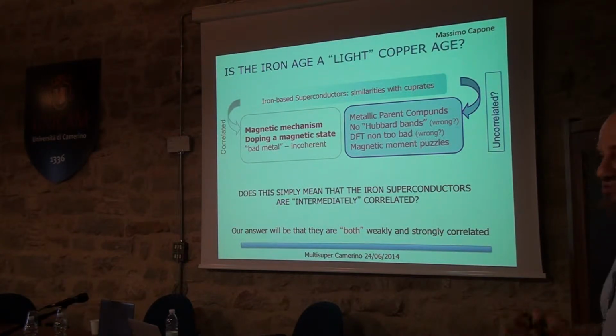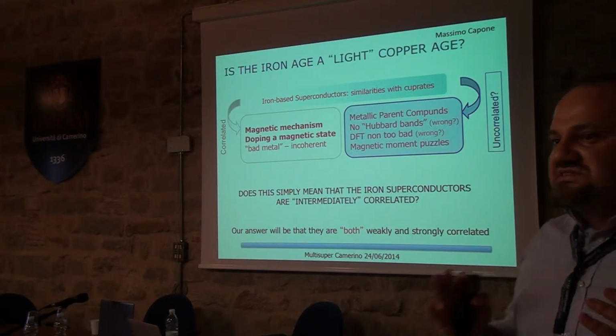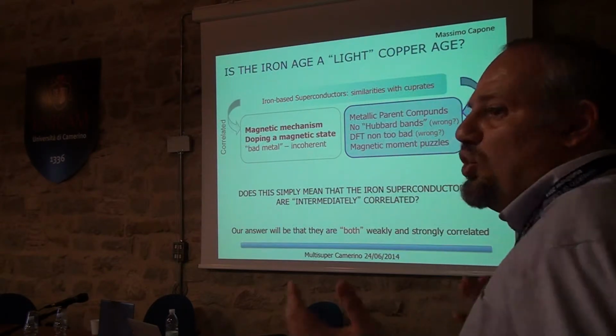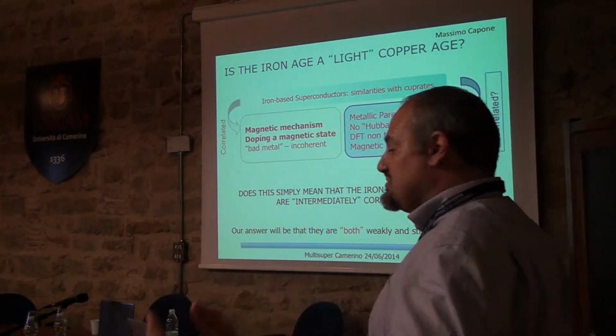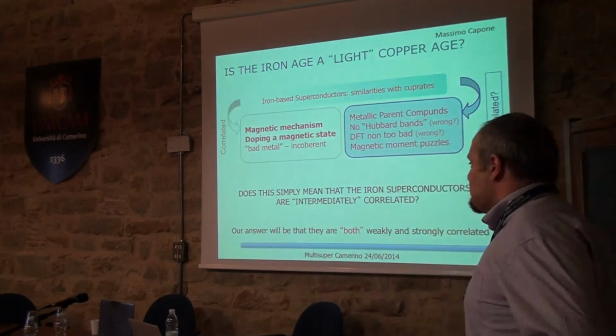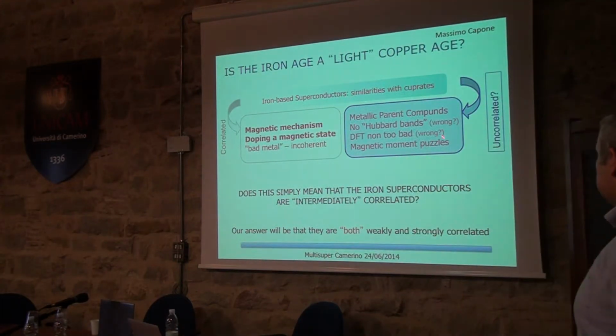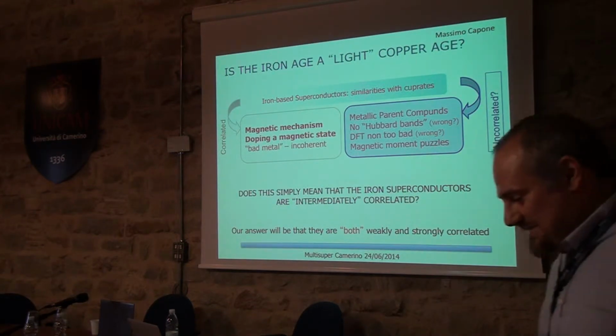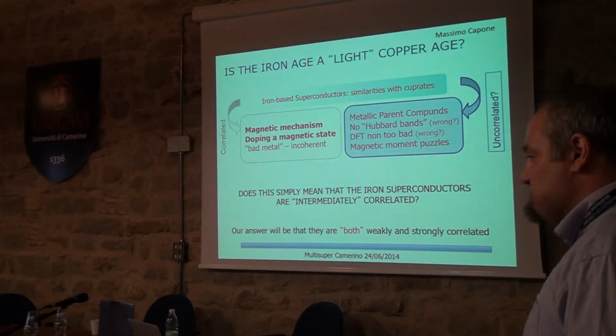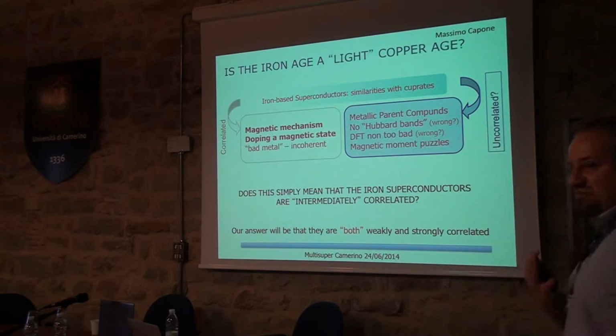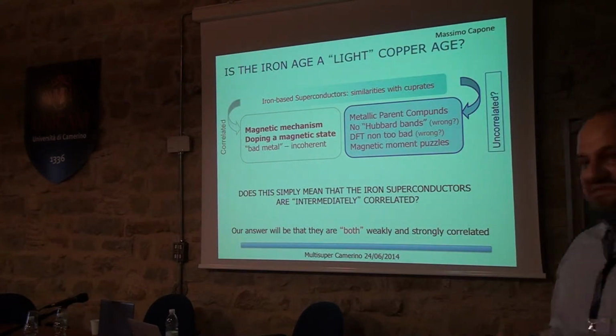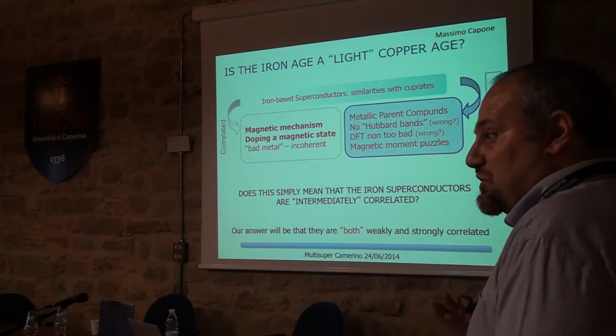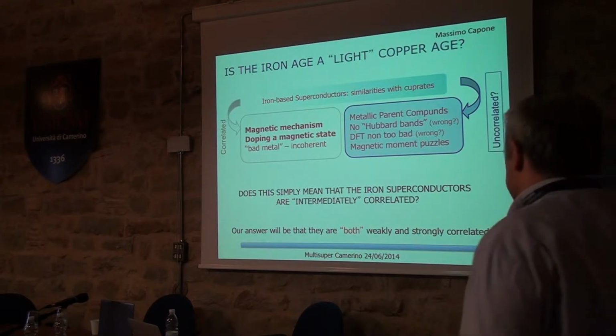So first of all, there's no Mott insulator in the parent compounds. So the metallic compound is anyway metallic. One of the other things is that people typically say that there are no Hubbard bands, which are the fingerprints of the Hubbard physics. Even though I'm starting to put a question mark on whether it's wrong, as Sergei is showing us in this ARPES data, that at least in some members of the family, the Hubbard bands tend to appear, even though they are not pronounced as in the cuprates, they are there.